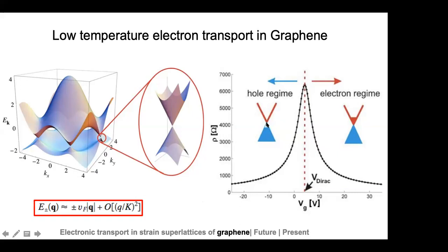Once you reach the Dirac point, theoretically, there is no state available for the charge carriers, for the electrons, because of which there are no charge carriers which can occupy this state. And so theoretically, the resistance of the system should shoot up to infinity. But what happens in reality is that the Dirac point is never reached precisely. There are always charge impurities, mechanical deformations, etc. in graphene. So in general, in the lab, it reaches a very high but finite resistance value.